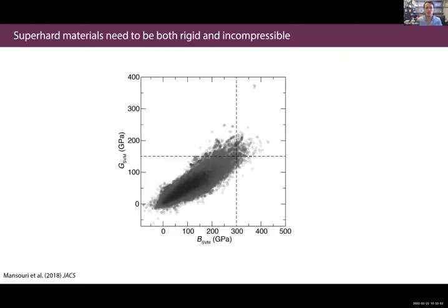And here's what we get. So what you're seeing now is the predictions with their errors. Remember, each one of these data points technically should have a little plus or minus 17 or whatever it is, gigapascals error on it. They're not perfect, but they're pretty close. You're seeing your predicted rigidity on the y-axis, shear modulus, and predicted incompressibility on your x-axis, right, your bulk modulus.